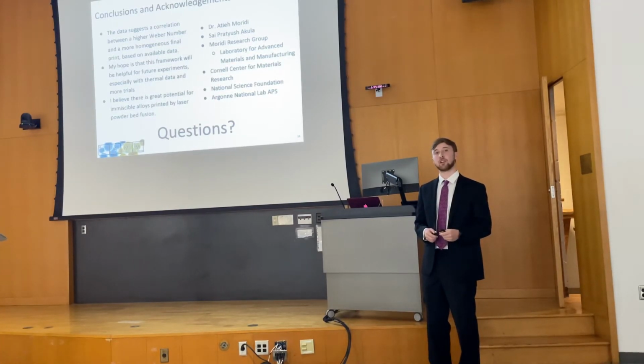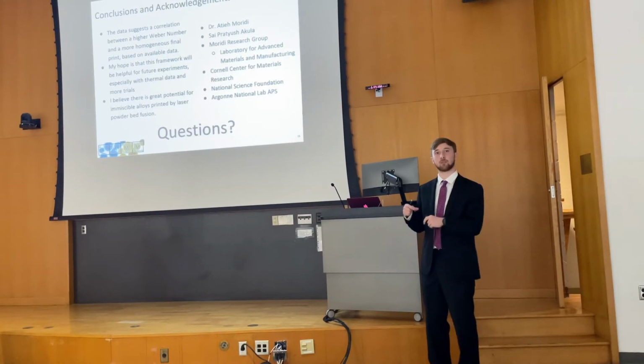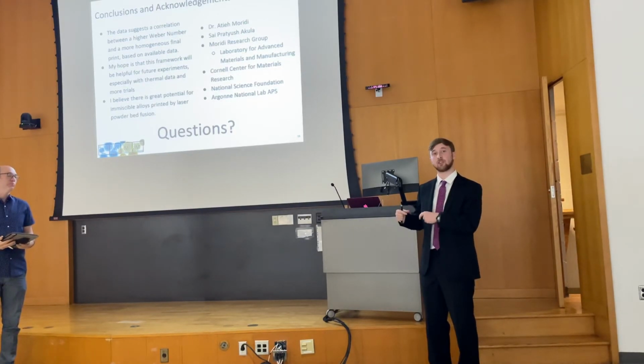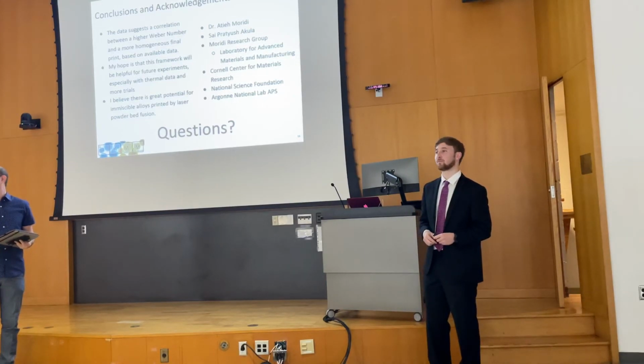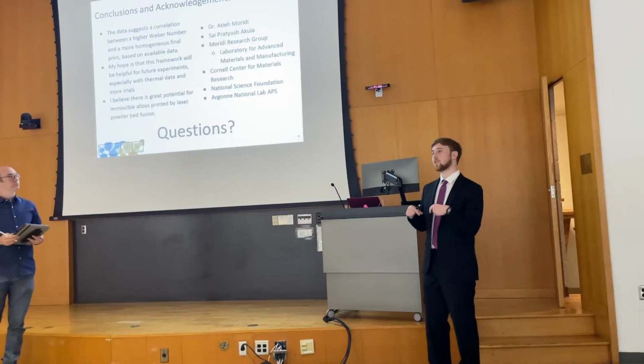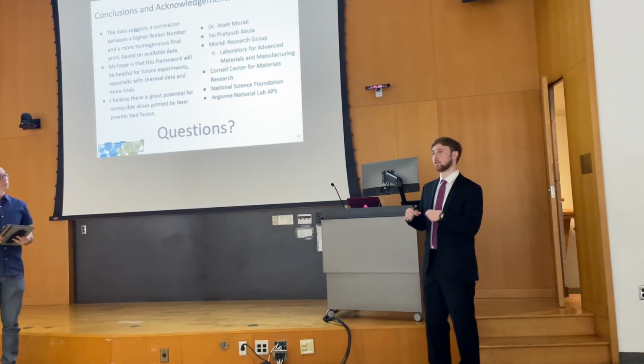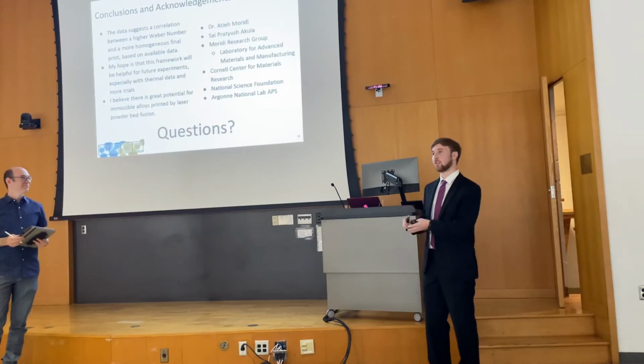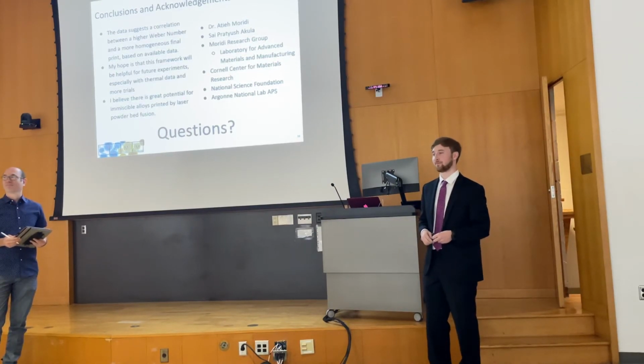The 50-50 ratio is, I believe, essentially a starting point so that we could develop a reliable way to print it, and then once we could, optimize those properties by changing the ratio. What benefits do you get from making an alloy more homogeneous compared to allowing it to be sort of separated? You get more consistent directional properties. So it'll have the same properties in different areas and in different directions, rather than if it was separated out by phases. Okay, thank you.